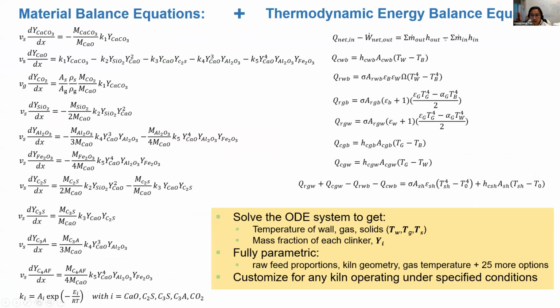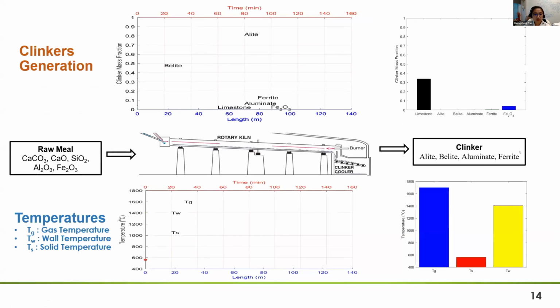So this virtual cement plant model has a large flexibility with more than 50 parameters, which could be designed and customized according to user requirements. Like we can easily change the geometry of the kiln, we can easily change the initial temperature conditions, and also change the location of the burners using this model.